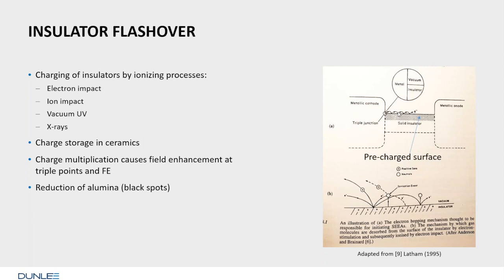Once field emission appears and hits the surface, this insulator charges. You would think it charges negatively. No, it charges positively because under certain regular circumstances, one electron going out and hitting the surface creates multiple electrons and ionizes the surface. So instead of getting negative, the surface gets positive and increases the field emission here from this spot. And that may create a flashover, and in some cases even a puncture if the charge accumulation is too high. So the insulators, going back to our bullets here, are maybe ionized during electron impact, but also ion impact, vacuum ultraviolet, and X-rays. And the ceramics doesn't forget easily.